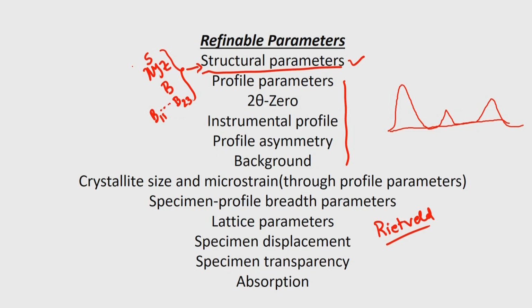So, we are not doing any other aspect. See, we took the powder pattern and decomposed it and identified some 498 reflections, used the Patterson approach and the direct method approach to get to the heavy atom positions. After that, the heavy atom positions were put in and a refinement was done. Before we could do all these things, we had done the profile refinement in the beginning. That is, we fitted every powder diffraction peak with a profile, and we refined the parameters that are associated, as is indicated here.